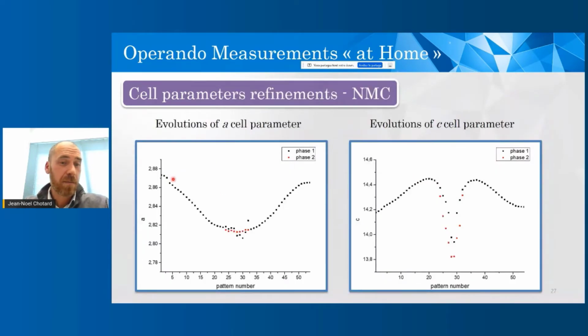We can, of course, do profile matching at least of those phases, and that's one of the examples. We can see in black the evolution here of the A parameter of NMC, and here on the right side the evolution of the C parameter. It turns out that, in fact, at the end of the charge, we have a biphasic domain, and you can see in red the cell parameters of the second phase, which was identified during the cycling.